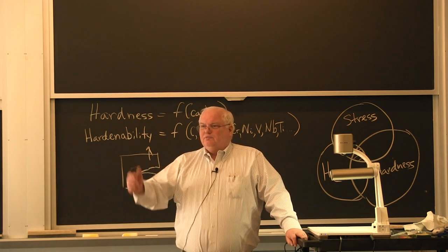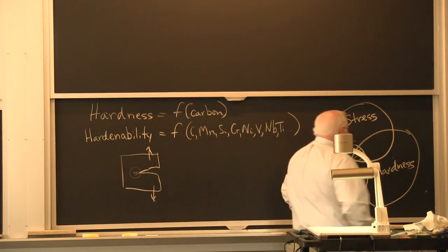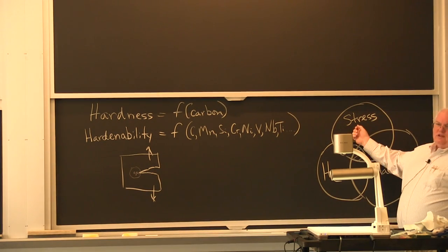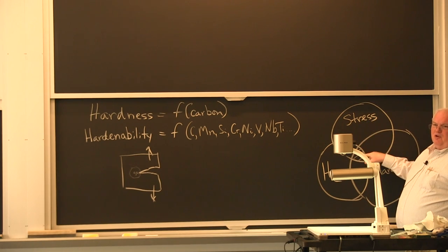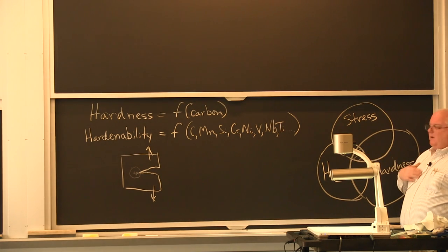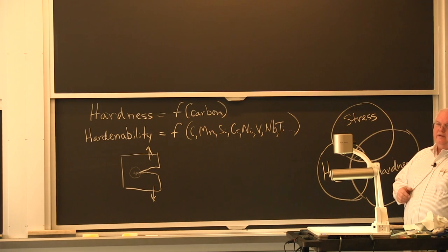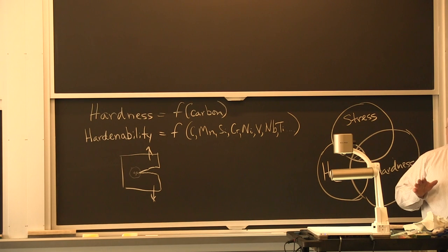Yeah, and if you're using mild steel, as you brought up the term the other day, it's almost impossible to crack mild steel. It's got such a low stress. The residual stresses from a low strength steel are so low, that circle is so small that you've got to really work. I tried to do it in the laboratory once and I couldn't get it done in a week, with a number of different things.